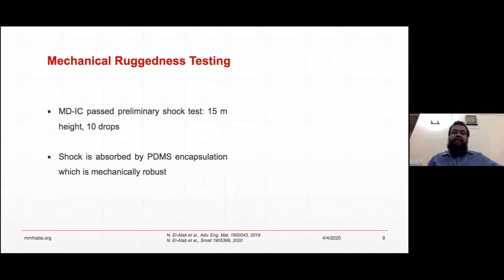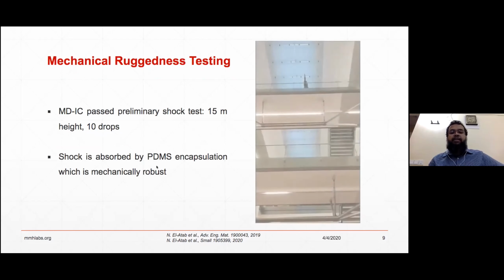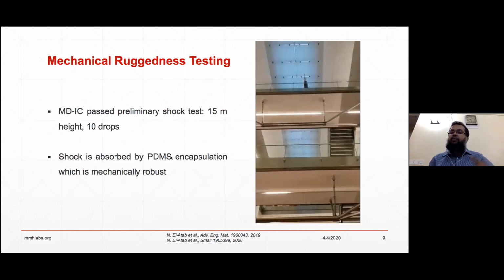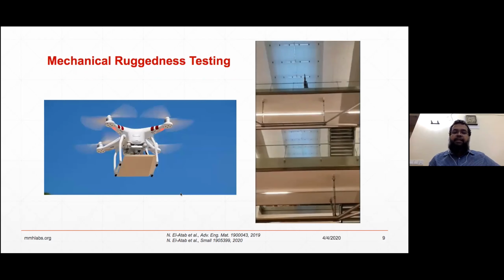So, mechanical ruggedness. We did shock testing, like from 15-meter height, we did 10 drops, and the shock is absorbed by the PDMS, the polymer-based encapsulation, which is essentially mechanically robust. You can see here that there are these UAVs. We flew them, and those were the ICs, and we just dropped them off. And here, this is from really high, tall buildings, and we see that they can actually absorb the shock.